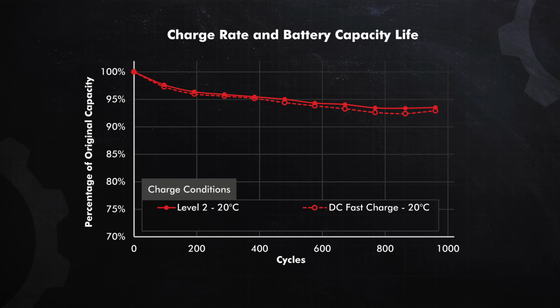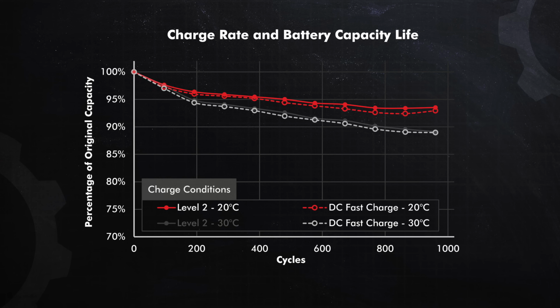very small. Interestingly, when they charged the cells at 30 Celsius instead of 20 Celsius, the increase in temperature had a much greater impact on battery capacity than the fast charging did. From this, it would appear that if an EV can properly cool its batteries during a fast charge, there should be little impact on degradation.